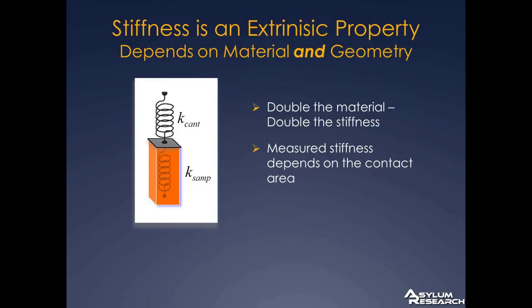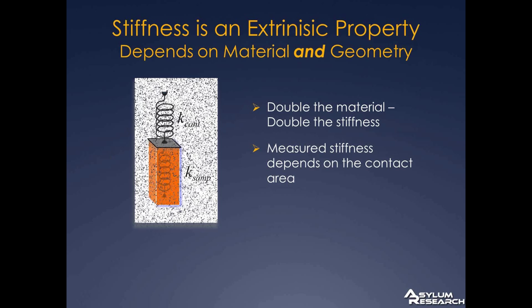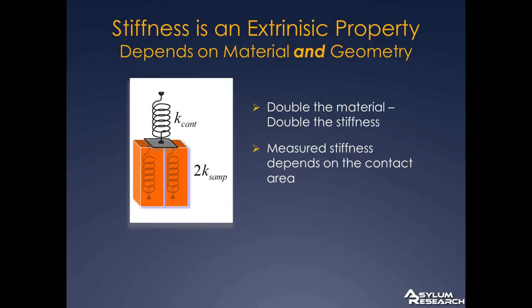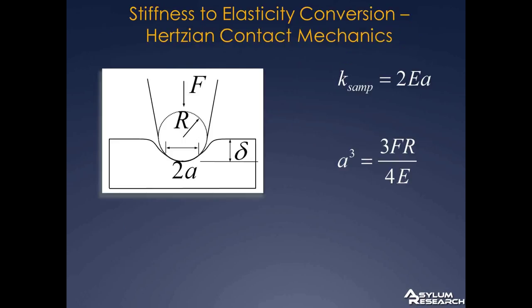And the idea is that if you take this material which has a certain contact area and you measure a K sample, then if I double that contact area, so now I'm touching twice as much material, I'm going to measure twice the stiffness. These are the same exact materials, so I'm measuring twice the stiffness, but that's not telling us anything intrinsic about the sample. It's telling us something about the contact area instead.